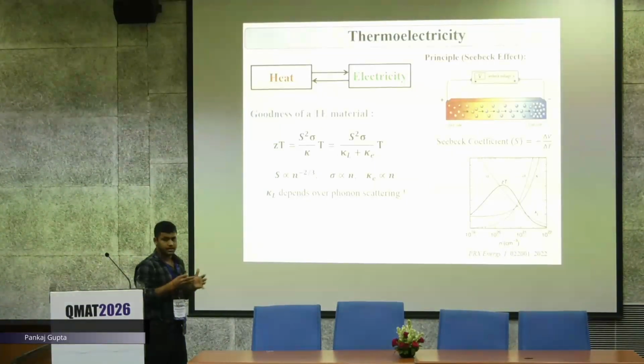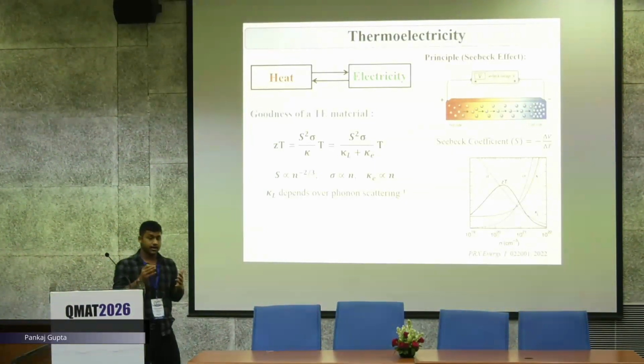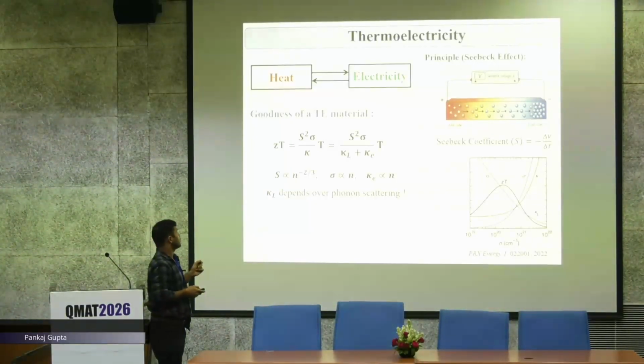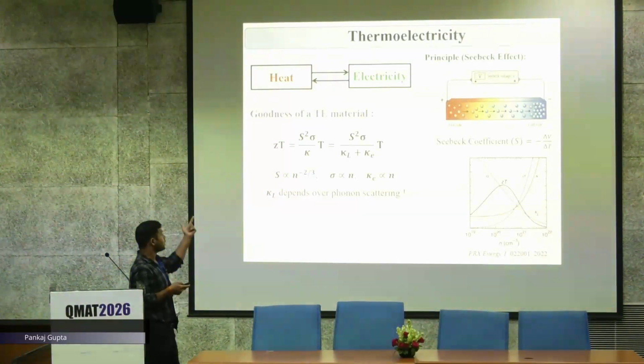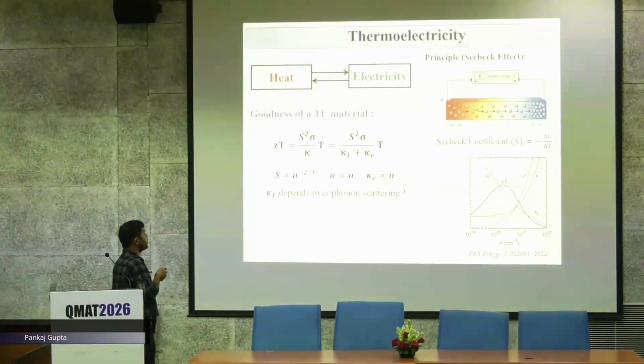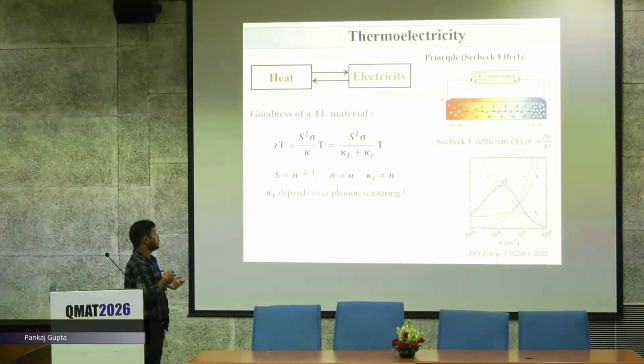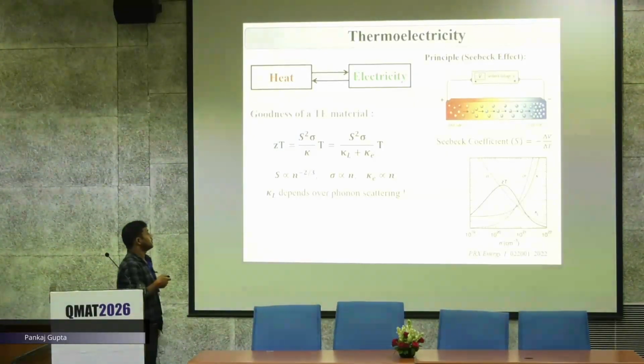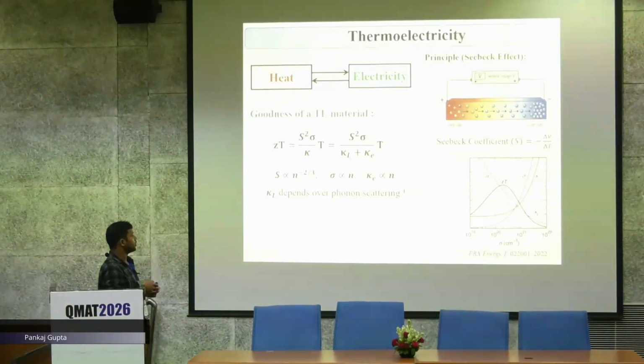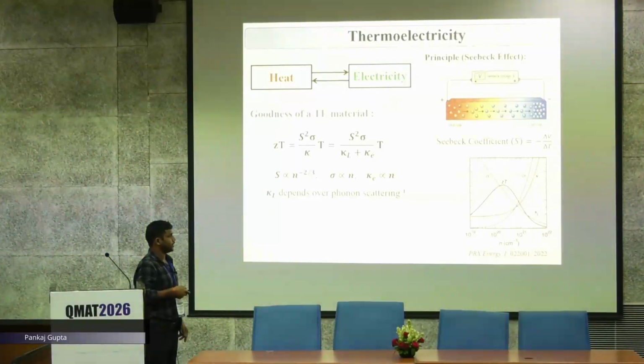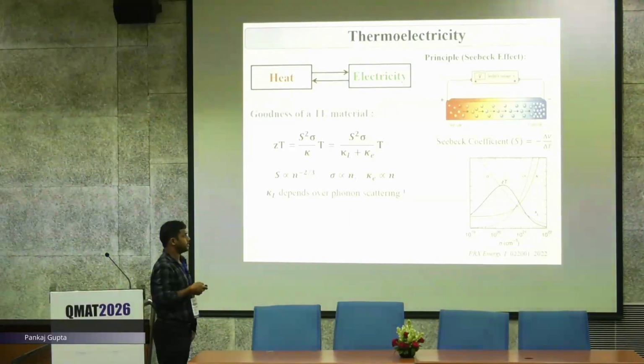But what defines the goodness of a thermoelectric material, and hence its conversion efficiency from heat to electricity? The goodness of a thermoelectric material is decided by the dimensionless figure of merit, called ZT. That is a function of the Seebeck coefficient, electrical conductivity and the thermal conductivity. This thermal conductivity can be further broken into two parts, the lattice thermal conductivity and the electronic thermal conductivity. This tuning is not easy because all these parameters are interdependent through the carrier concentration. As you can see from this plot, everything is dependent on the carrier concentration, and we need a certain optimized carrier concentration to get higher ZT.